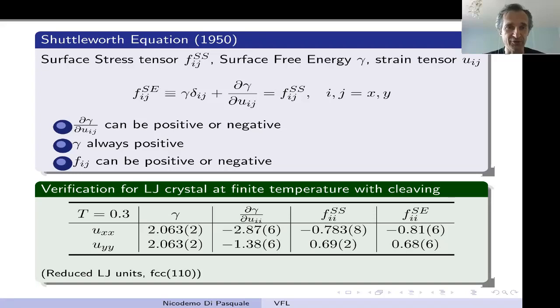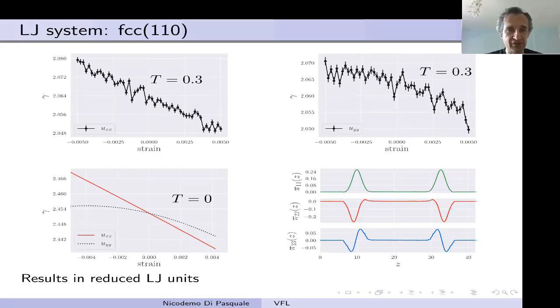So in the initial part of our research, we settled on establishing some relations between surface stress and surface free energy, which were well known, but the debate was still out there about what exactly these things measure. So we verified on a very simple Lennard-Jones crystal that indeed the understanding of surface stress as work per unit area done by the surface which is stretched is linked to the surface free energy, which is the work of creating a unit area of the surface or interface. Next slide, please. These are just the details of how we measured these properties for the LJ system.